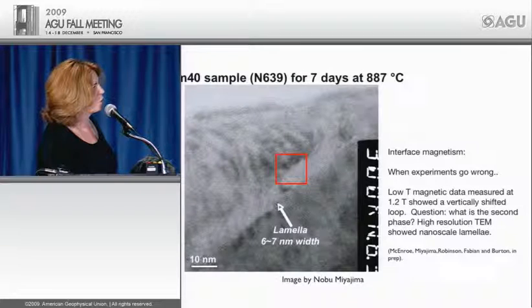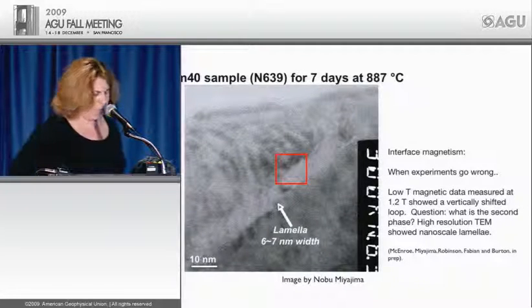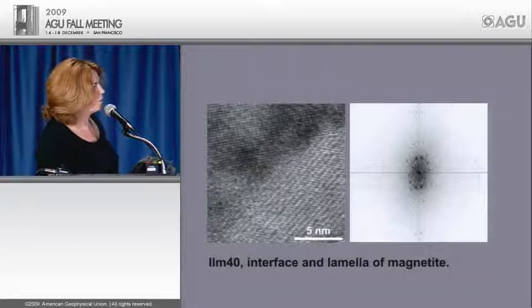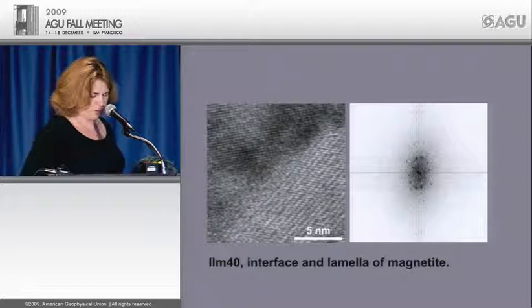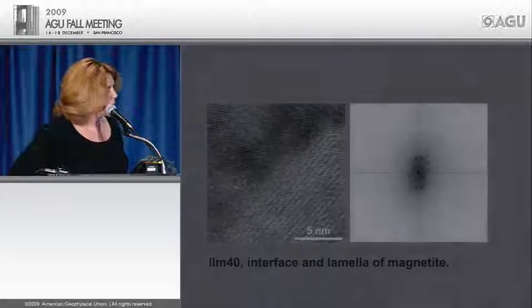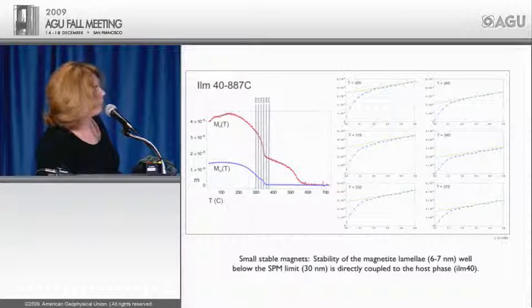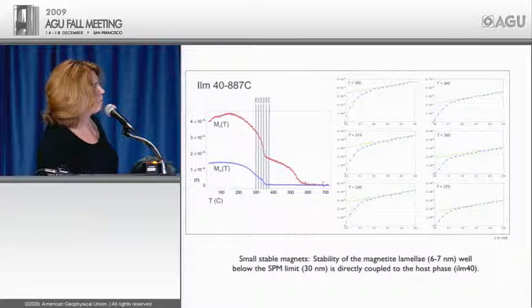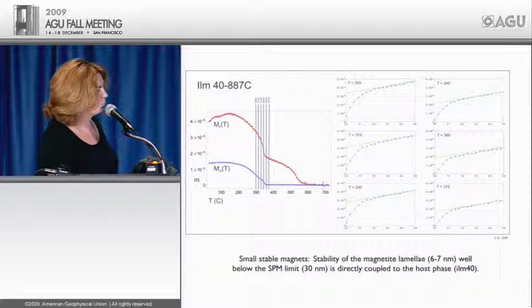We did a lot of magnetic experiments. We went to the TEM. And what we found is there's both ilmenite 40 and there's magnetite in the sample, but the magnetite's only 6 to 7 nanometers wide. And what we see here is some Mr and Ms curves, and you see with in-field magnetization that we have a high magnetization which is lost at about the unblocking temperature of the ilmenite 40, but then we continue to have a magnetization from the magnetite.